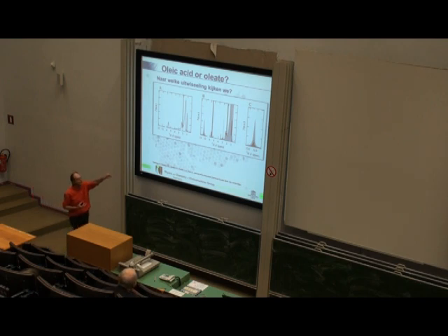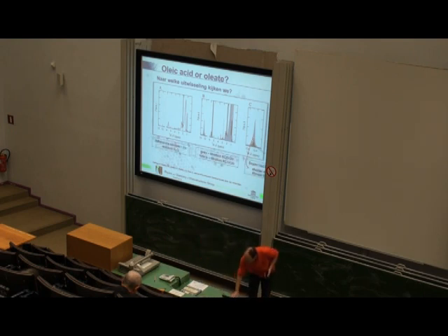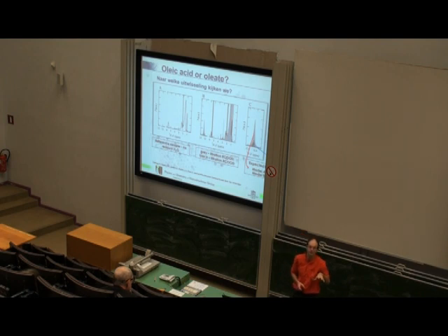And that's shown in the third panel, where the black line is again the measurement, the dark gray background. That's what we expect for the scenario where the oleate is on the surface and the light gray background is what we expect for the scenario with the acid on the surface, given the purity of the deuterated oleic acid. You see, we are very close to this scenario B. And actually, the fact that we are just a little bit above, I mean, we can only lose.